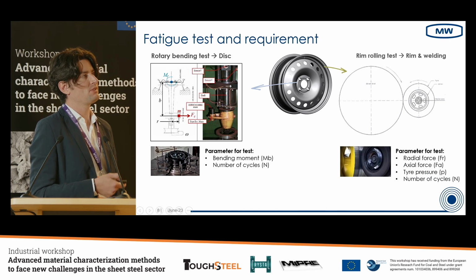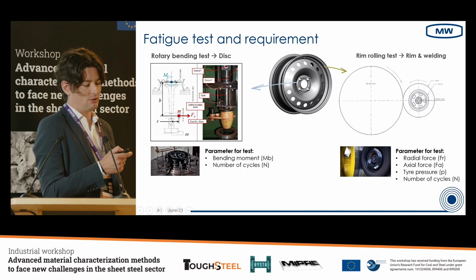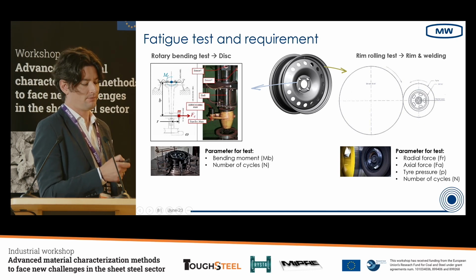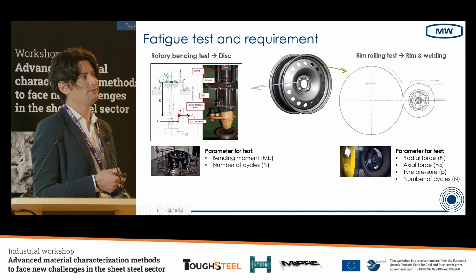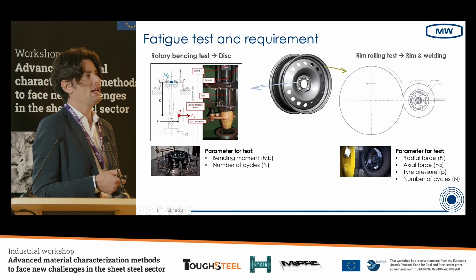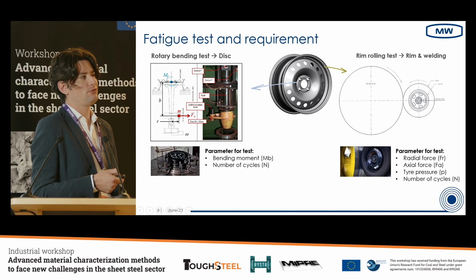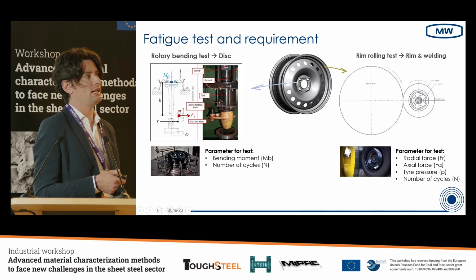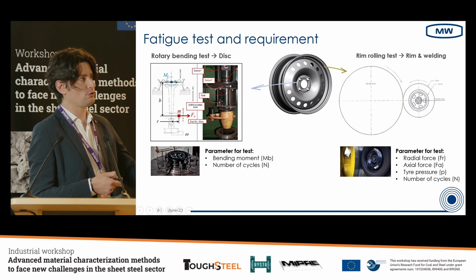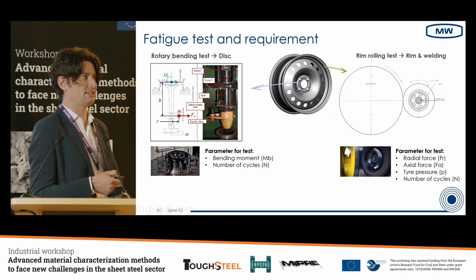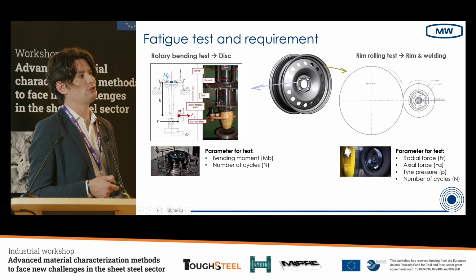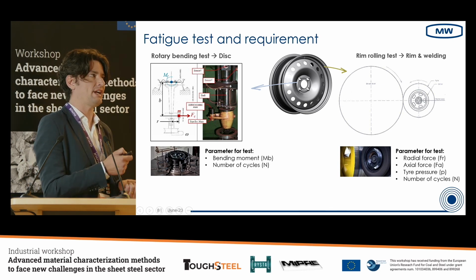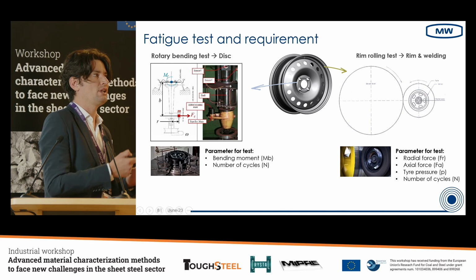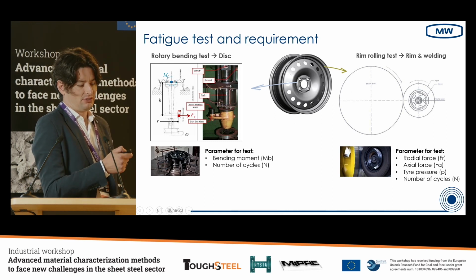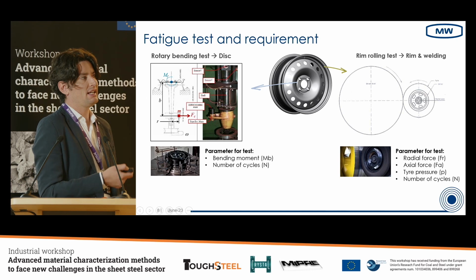the number of cycles that the wheel should reach. The second test is the rim rolling test, in which we put the tire on the wheel, and we push the wheel against the drum and set it in rotation. In the test, we can apply only radial forces, or if we introduce a relative angle between the axis of the wheel and the axis of the drum, we can also introduce an axial force in order to simulate the behavior of the wheel in a corner. Also in this case, we have the pressure, because we have the tire, and the number of cycles.